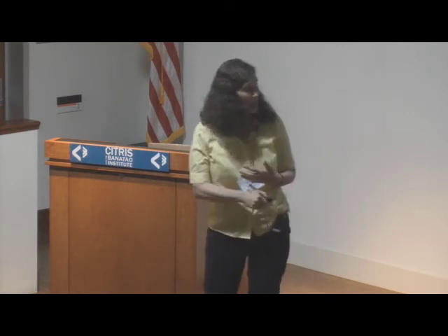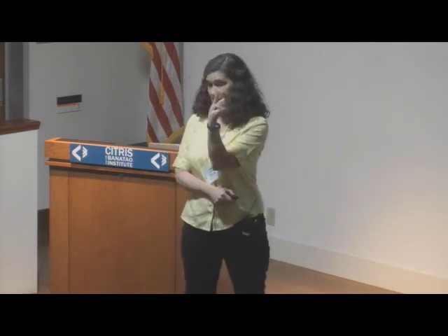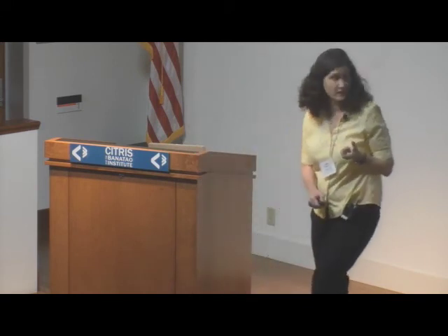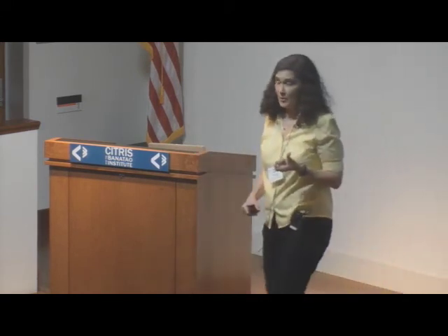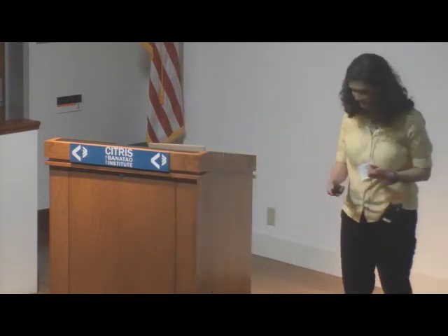Now, there's a couple things I should tell you. First of all, this is diffusion of lithium within this aqueous fluid. So this blue schist, we're assuming that the fluid is traveling through the blue schist, but it's not traveling through the eclogite, but we have this little diffusive profile of the lithium diffusing through a fluid around the grain boundaries. So we have to take into account porosity when we're thinking about this kind of estimate. We have to take into account partitioning between the minerals and the fluid. We have to take into account a lot of factors. But we can at least constrain, because of the short distance of this profile, that the duration of the fluid infiltration is likely less than about 100 years, which, you know, I said a million years was short before, right? 100 years is extremely short in terms of geologic timescales.